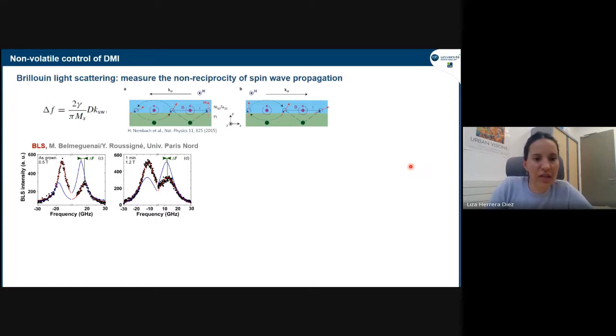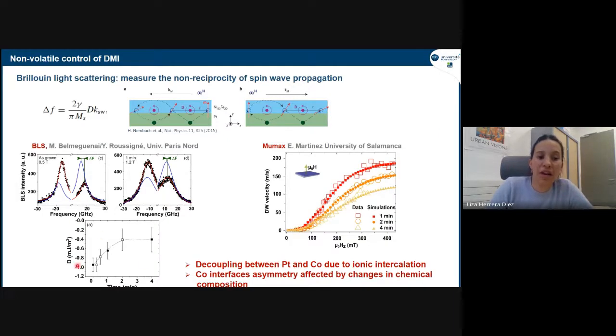This we did with our colleagues in Paris, who are the experts on BLS, and we could obtain the values of D, and we could see that it has a negative sign, but in absolute value it is decreasing as a function of the gating time. So we thought about this, and we know that the ions can go very far. This is the proof that there is something going on, because in these systems, the DMI mostly comes from the interface with the bottom heavy metal atoms. So our interpretation is that these ions are probably decoupling the platinum and the cobalt layers due to ion intercalation.